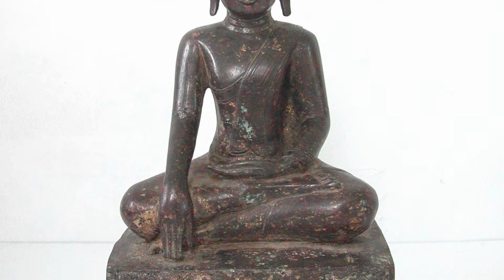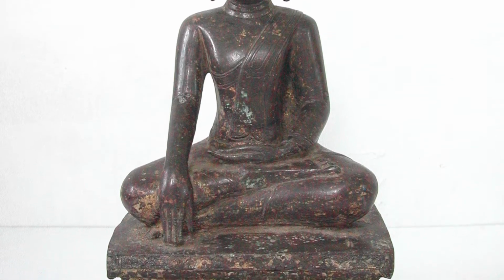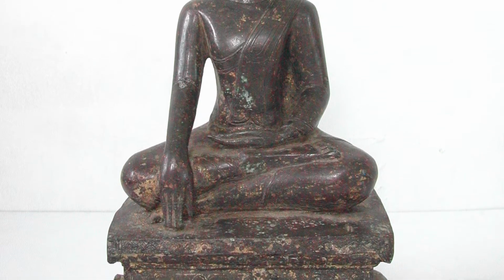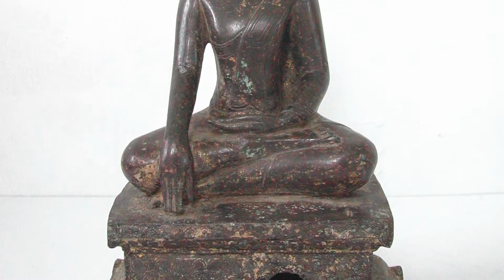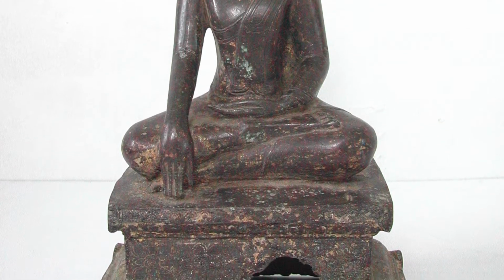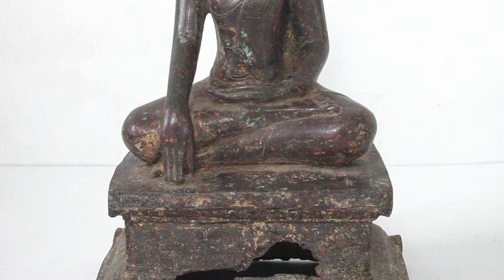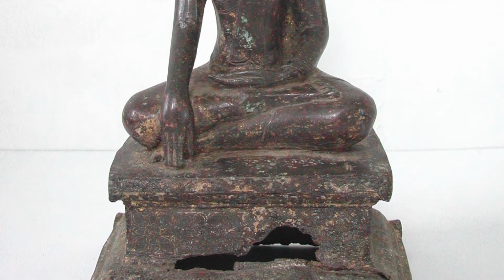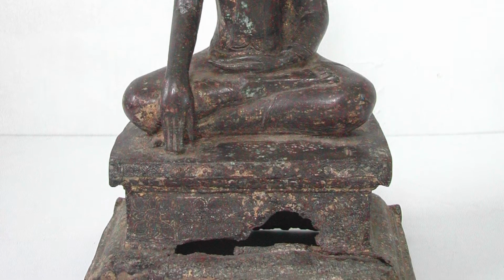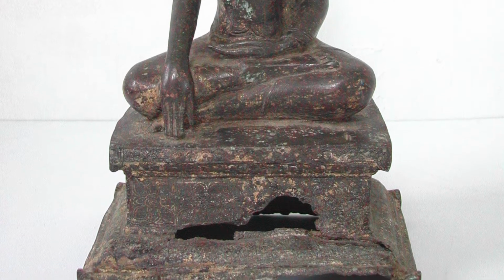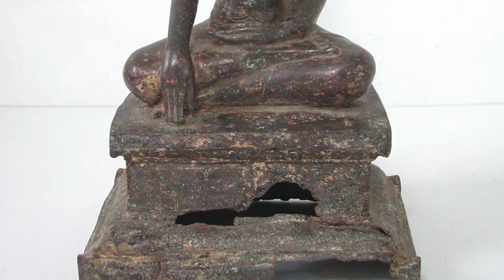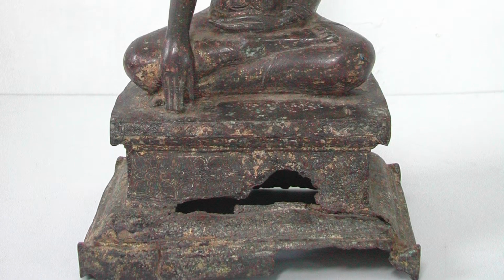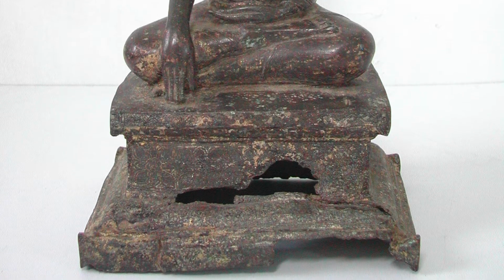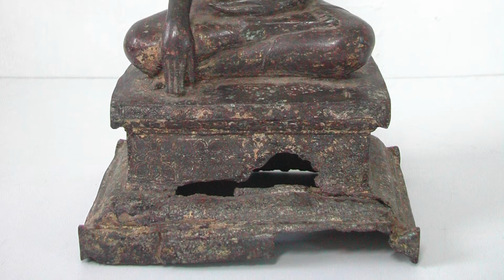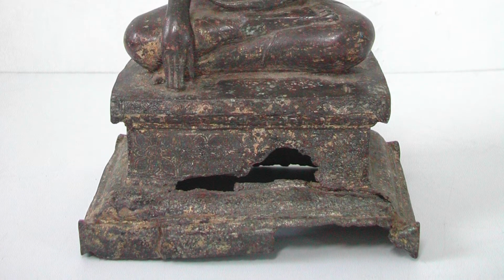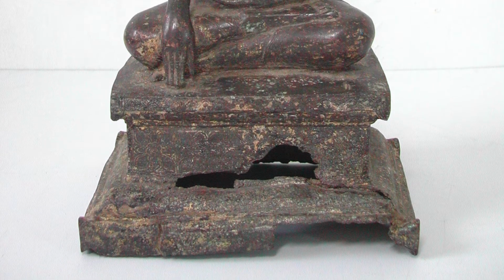There is an older attempt of a botched restoration. Various small areas all over the surface have active copper chloride corrosion that needed to be addressed. Otherwise, the figure is in good condition. As found in most ancient buried bronze sculptures, the metal alloy is heavily mineralized and therefore lost its solidity and is slightly brittle and fractures mostly along intergranular corrosion.